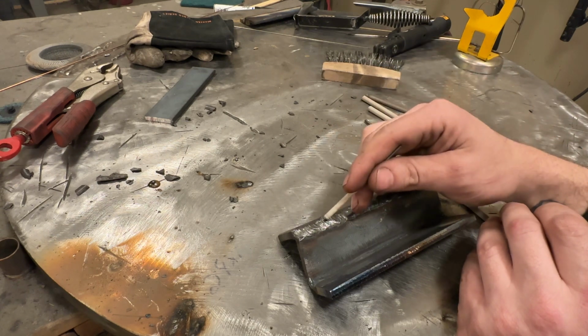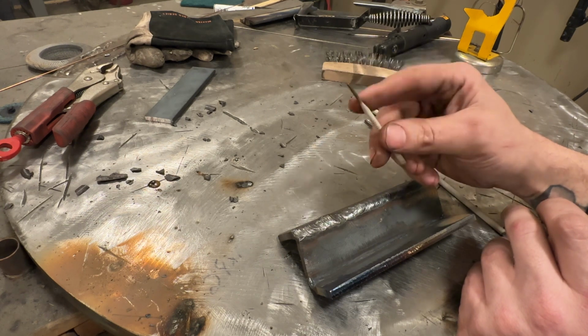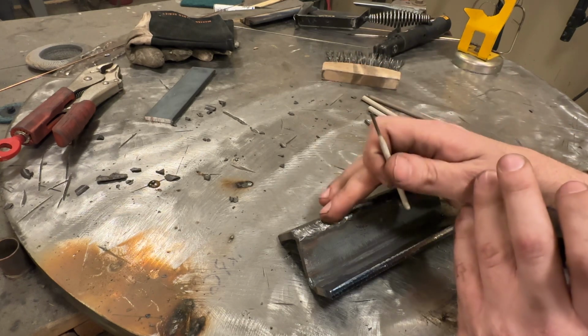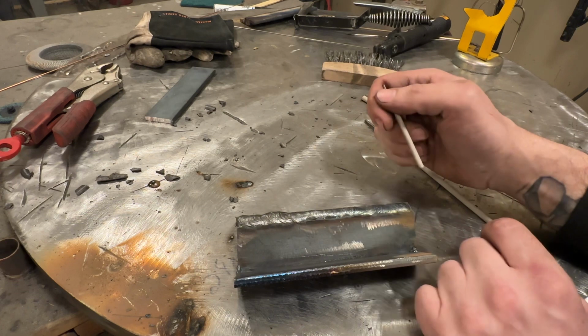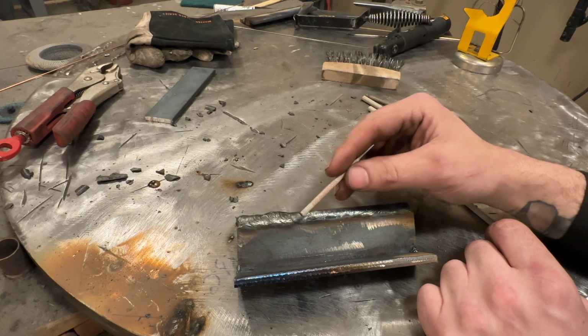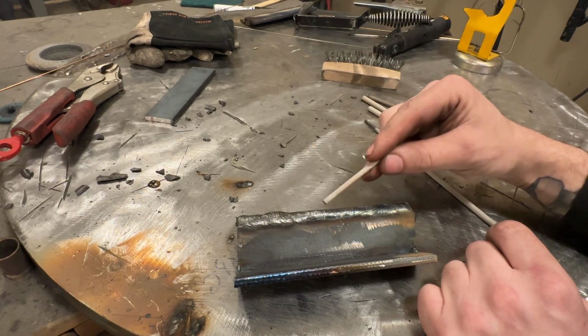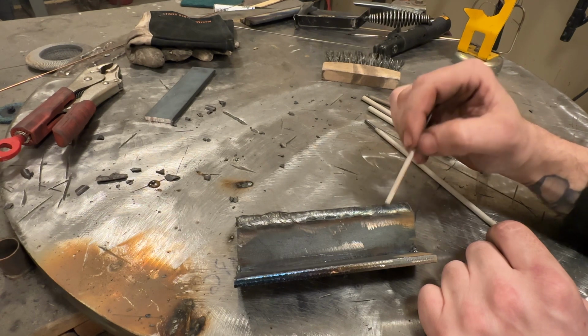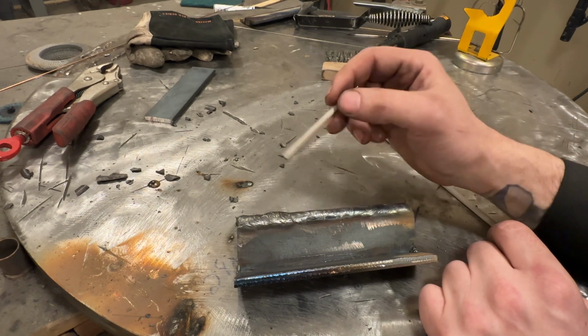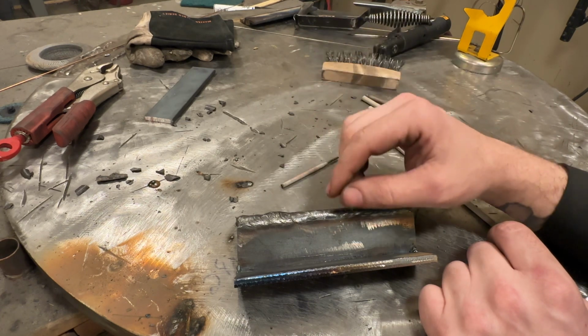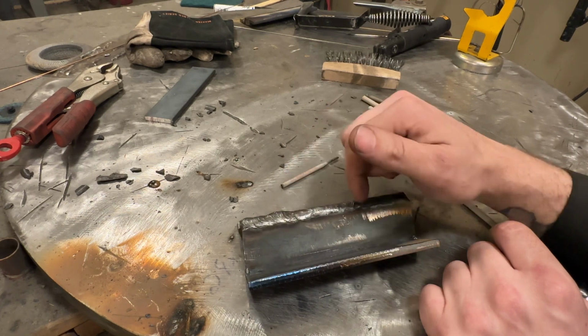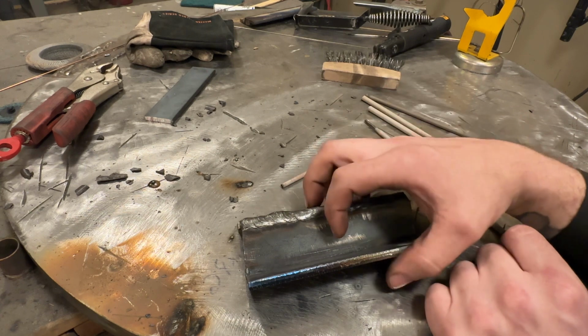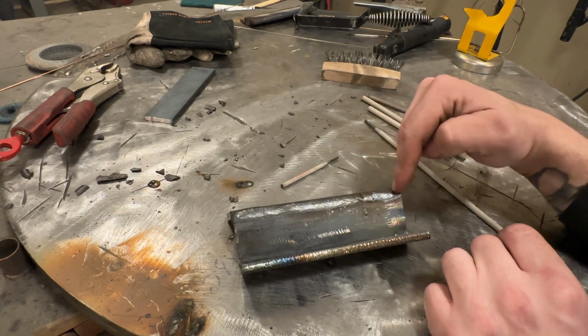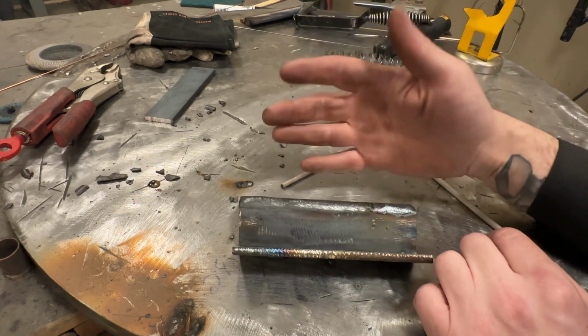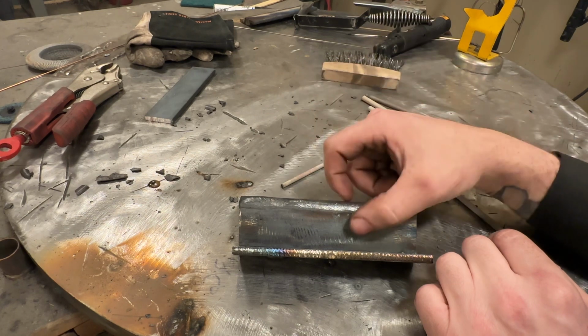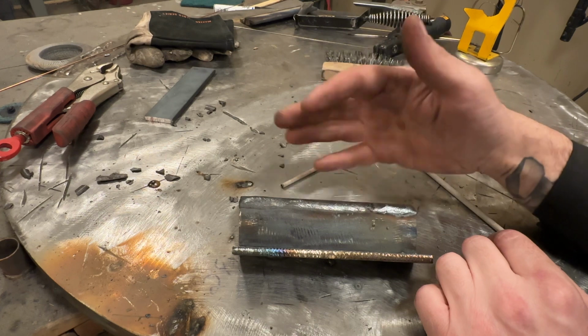And it's not to say, like I said, that this right here will actually blow testing results for the rod spec. It may not, but let's be honest, what's the probability here? You saw me do these welds. Which do you think would fail first from a standpoint of strength? I bet this one. This, where I did the root pass and capped it, and this one, which is just a straight pass, I bet will be less likely to fail than this from a strength perspective, or have higher tensile strength per se. Not to mention, I don't really know what the fusion looks like in that, or I guess really any of these, but that especially. And from a defect standpoint, I could almost do a weld like this blind. I mean, it's so much easier to run a bigger rod on big thick plate and get a decent looking weld that's free of defects. So all things to consider.